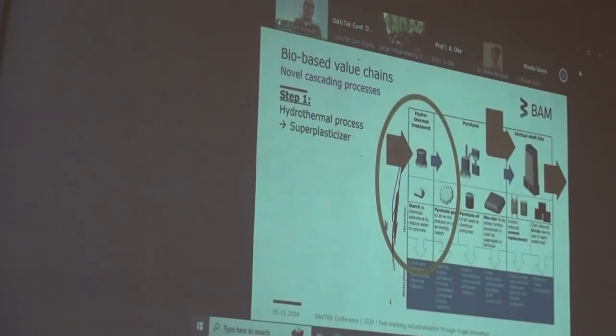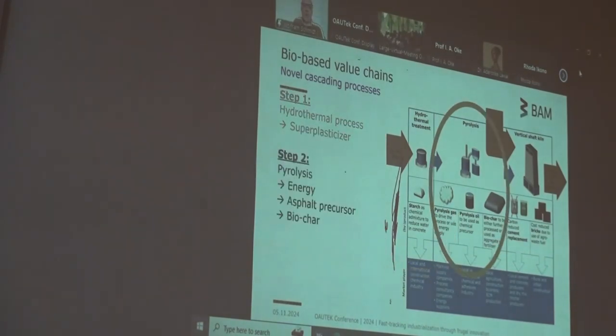Here we have developed some technologies where we use bio-based wastes, which means agricultural wastes like cassava peels, and first of all we boil them in order to obtain a superplasticizer. Secondly, we pyrolyze them, and that gives us energy, so we have an energy yield. It gives us a condensate which can be used in asphalt, and it gives us this biochar which could already be used as a carbon negative concrete aggregate.